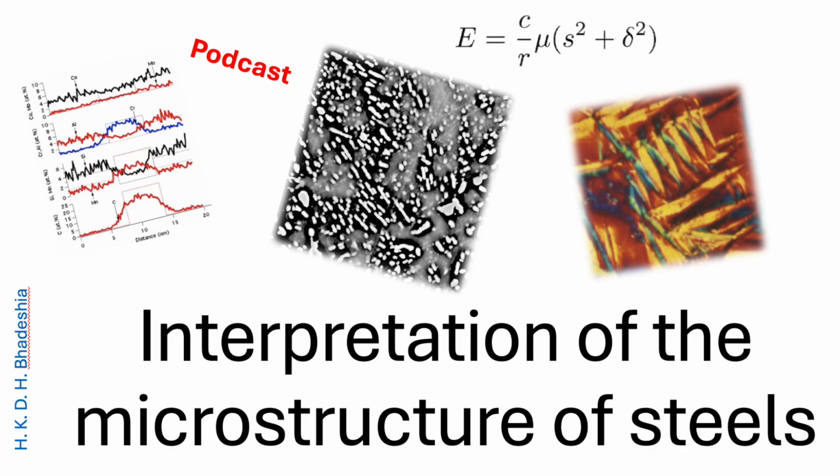And to map all of this, you really just need two diagrams. First is the iron-carbon equilibrium diagram that governs the basic composition. Is it a hypoeutectoid steel or a hypereutectoid steel? Less carbon or more carbon than that sweet spot. And the second one is the big one for today: the time-temperature transformation diagram, the TTT diagram. This is the key to our deep dive because it shows what happens when we introduce speed, time, cooling rates. Yeah. And that brings in all those non-equilibrium structures that really define modern steel performance.